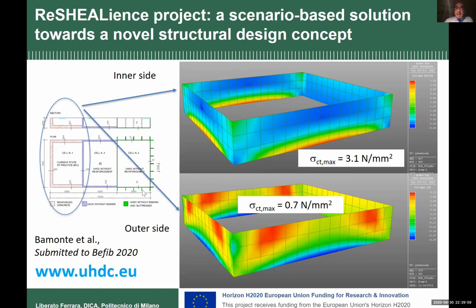We extracted the tensile stresses on the inner face and on the outer face. On the outer face we have some tensile stress, very low, 0.7 Newton per square millimeter, a little bit higher just at the clamped edge on the bottom on the inner side. But anyway, the tensile strength, 3.1 Newton per square millimeter, is close to the flexural tensile strength of a regular concrete. And considering that you will have ordinary minimum steel reinforcement, this level of stress is surely coherent with the design.